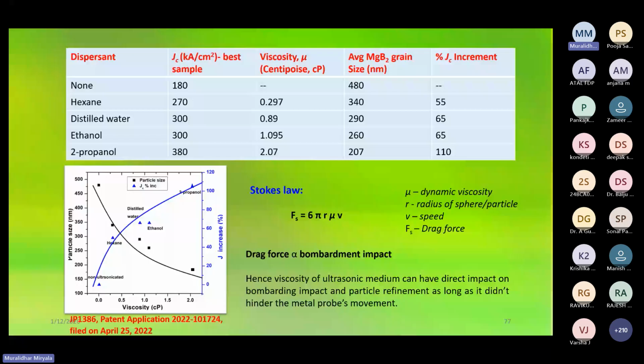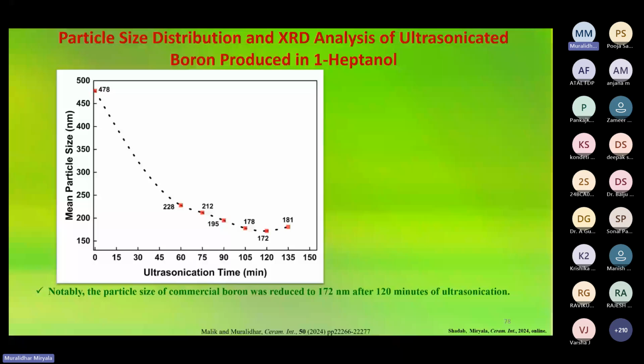As a result, the particle size goes down and Jc increases when the viscosity is increased. So we used high-viscosity heptanol. Heptanol is a high-viscosity material. Notably, the particle size went down to 170 nanometers. This is, up to date, not reported by anyone.